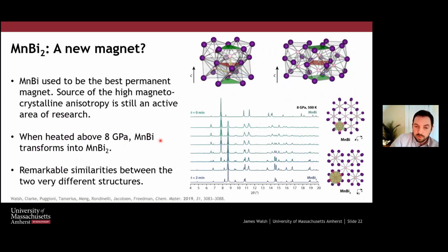So we have manganese bismuth, another system. Again, the 1-to-1 manganese bismuth was already known. This is a permanent magnet material, as I said, that was investigated heavily in the 50s for technical applications, but still now you'll find papers where people go back to this 1-to-1 compound and try to understand where its magnetocrystalline anisotropy comes from. What we were able to do is take that compound, heat it under pressure, and create a new compound, manganese bismuth 2, so the 1-to-2 compound. It's actually analogous to the iron bismuth compound.